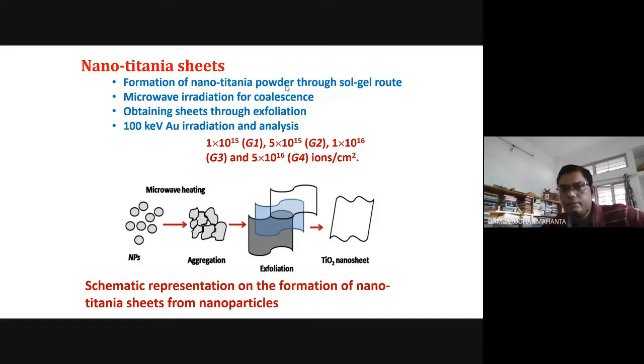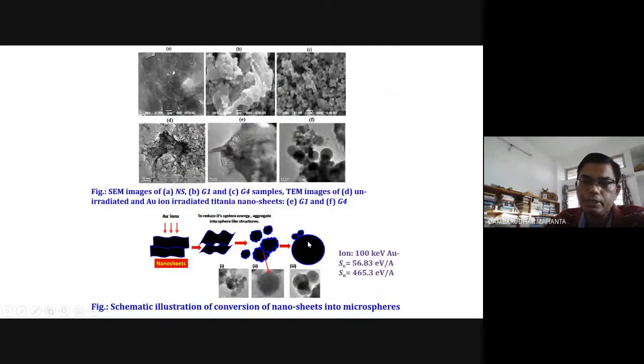Now, formation of nano-titania powder is very easy, and there are three phases: anatase, brookite and rutile. Anatase is very important, and here we used microwave irradiation for coalescence, and we obtained sheets through the exfoliation principle. After obtaining exfoliated seeds, they were subjected to gold irradiation, thinking that we can have something like a plasmonic response in this material. This is a cartoon showing nanoparticles which are seed materials. Because of microwave heating, they are aggregated. After aggregation, you exfoliate them and obtain titania nanosheets.